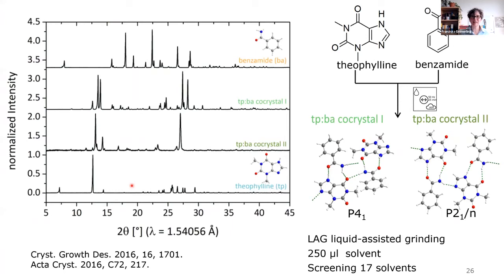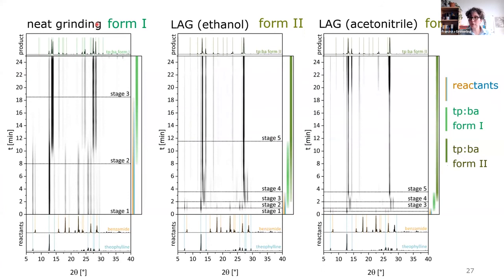So this is a system we have intensively studied. I will not go into super great detail. It's theophylline and benzamide. And this compound has again two polymorphs. And as we know already, we have a different way of formation if we perform the reaction under neat grinding conditions, or if we use polar solvents in comparison, then we end up here with form one of the polymorph, or in the other cases, we have form two.